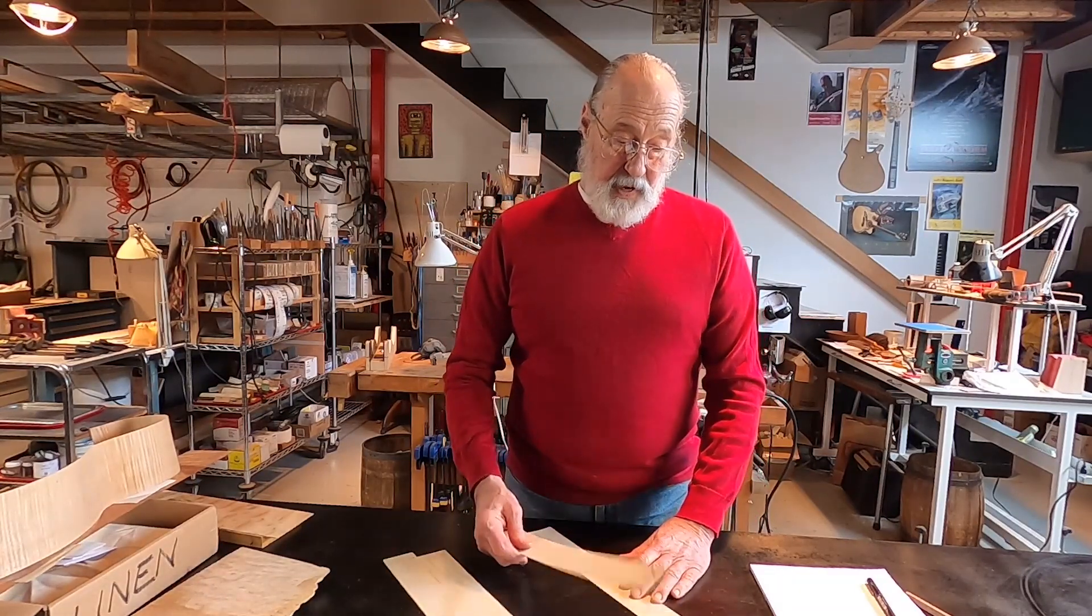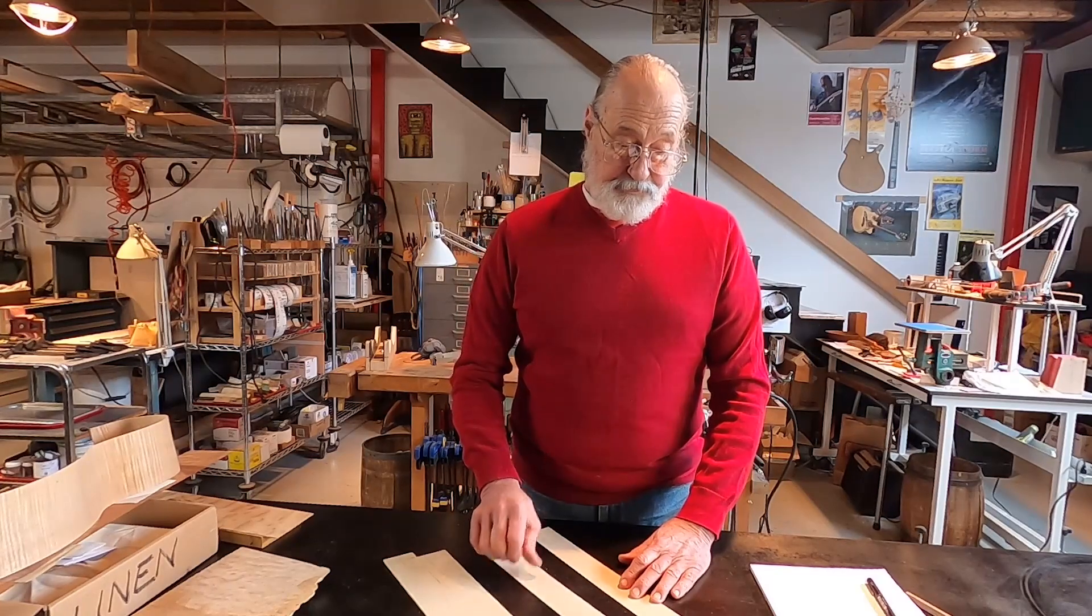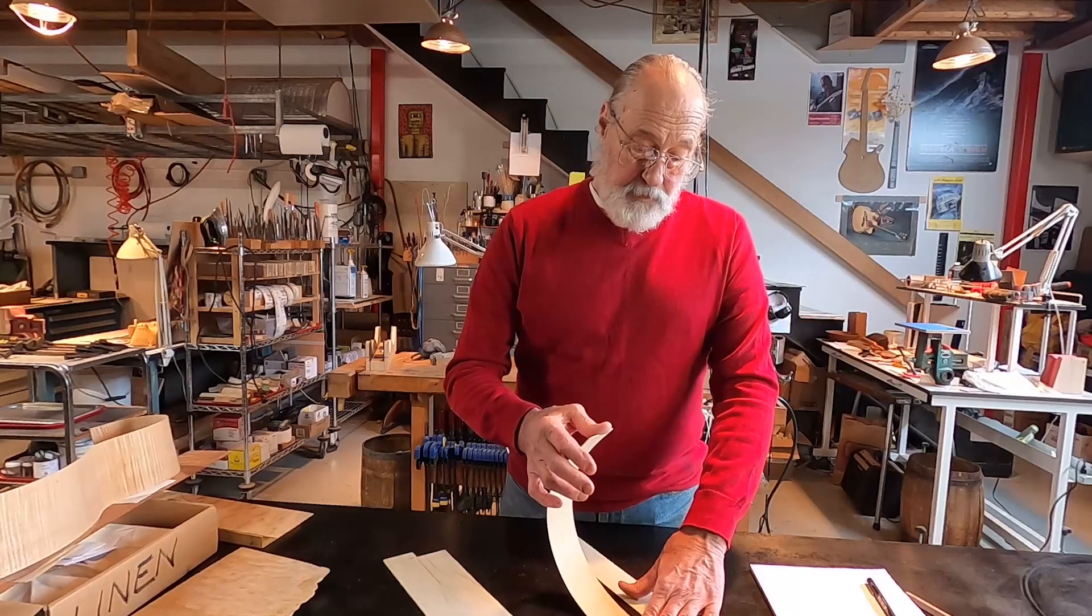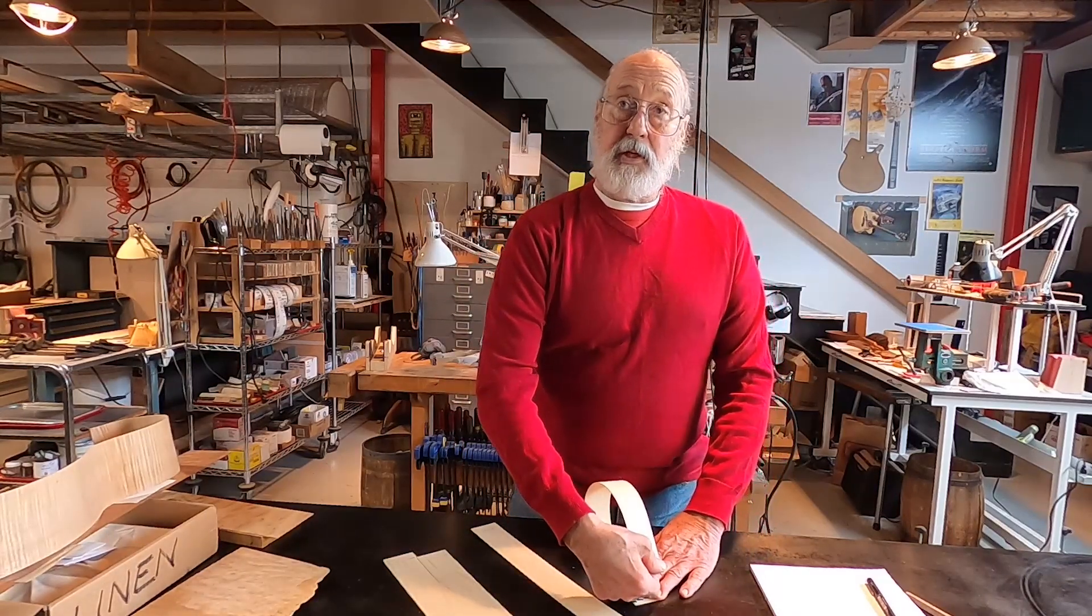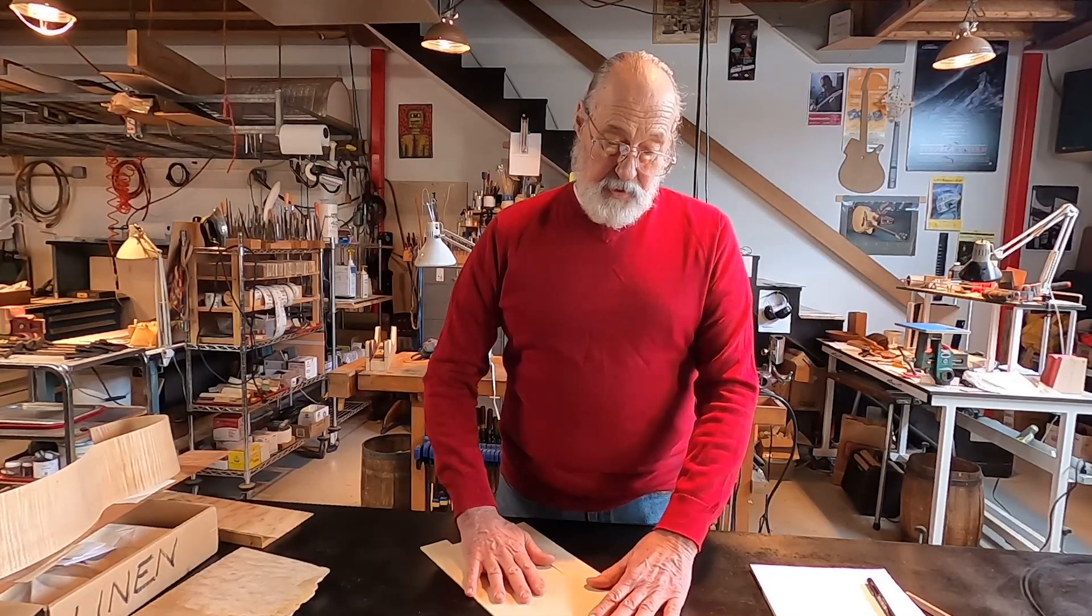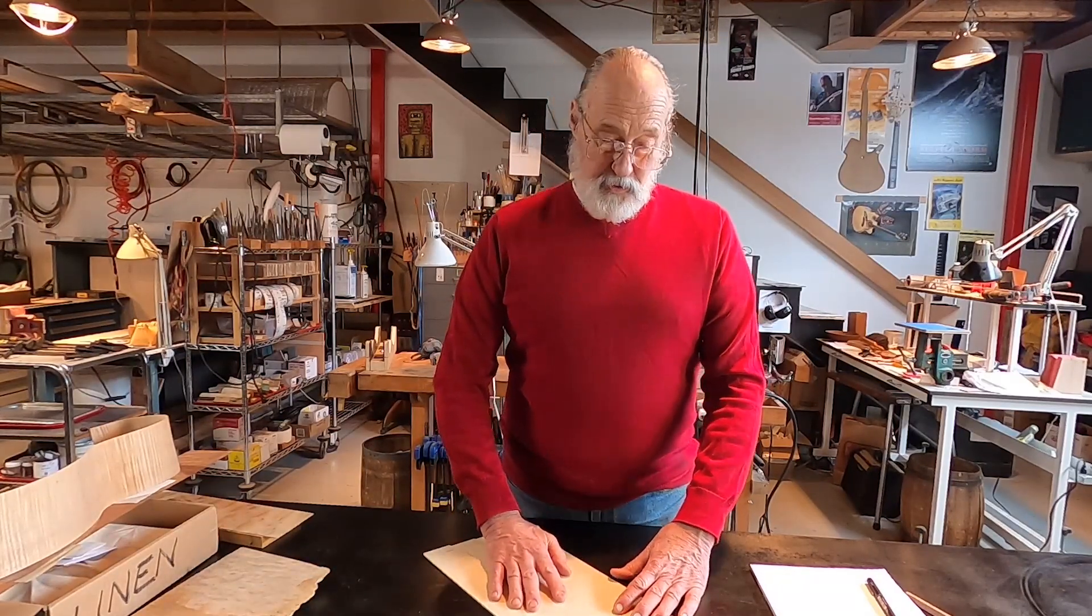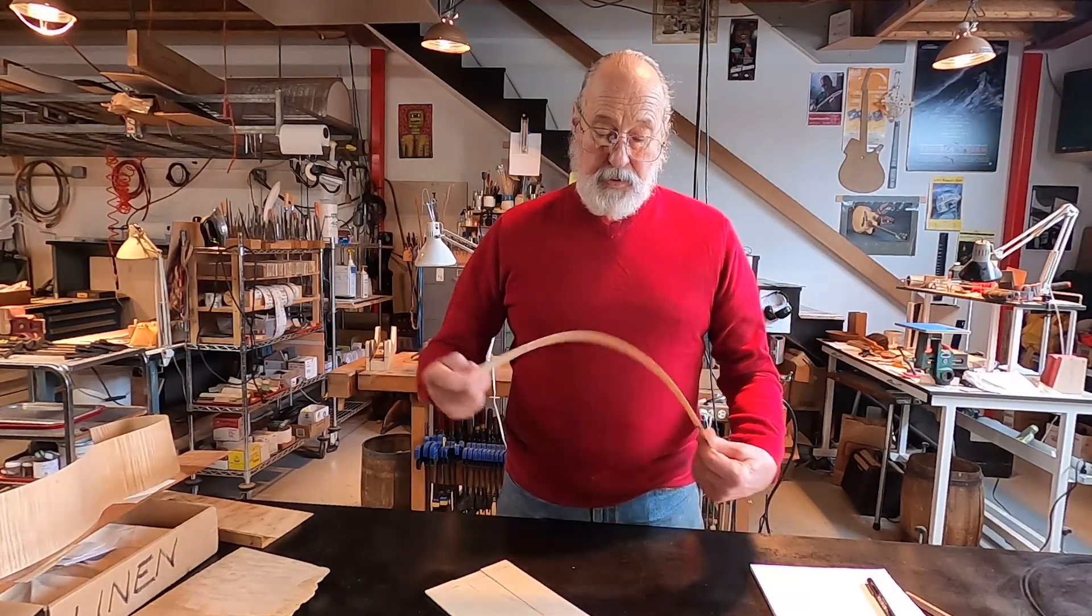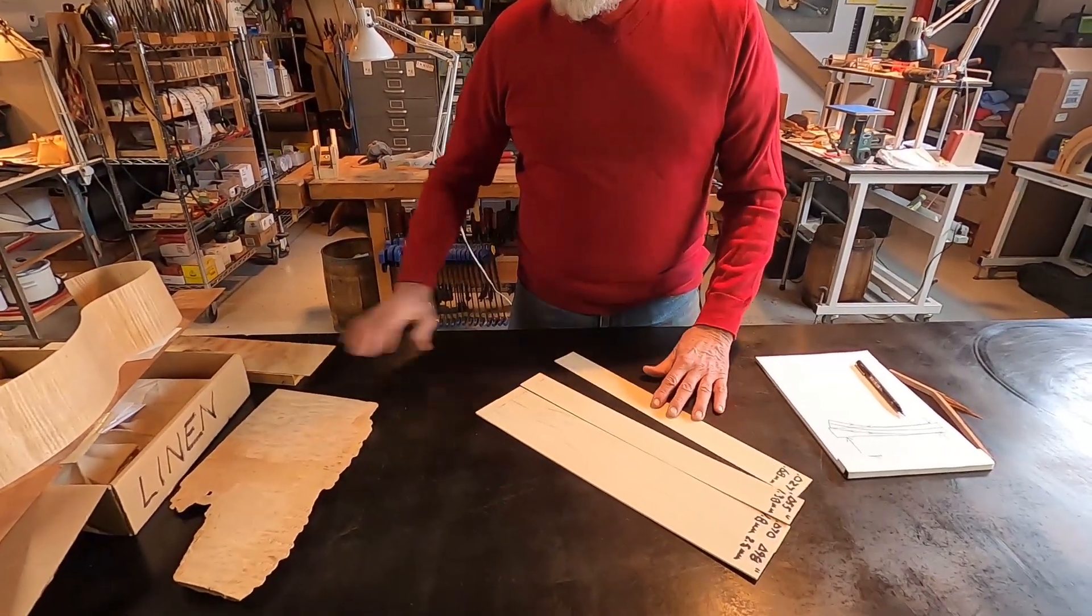So a small change in thickness means a big change in stiffness. Again, the cube function. So this 55 thousandths piece is about eight times stiffer than this 27 thousandths piece. And that's important to remember, that bending thick material is tough stuff, it really is. And if you want to make things easy on yourself, you'll try and use the thinnest wood consistent with the results that you want. This is straight grain material. We can do a lot with straight grain material in thin pieces and it doesn't bust.